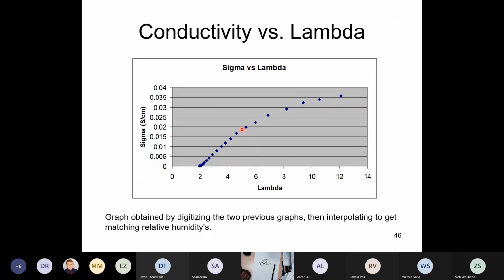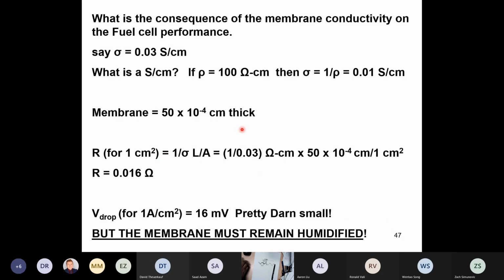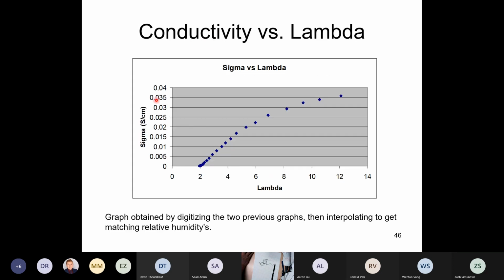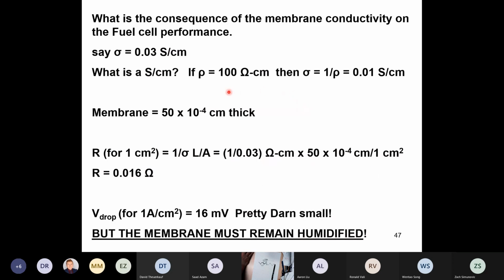Yeah, we'll just do one more slide because it's a good place to end after the next slide. So what's the consequence of this membrane conductivity on fuel cell performance? You can see about 0.03 Siemens per centimeter. This would be a decent value of the conductivity. So what is a Siemens per centimeter? Well, if rho is 100 ohm centimeters, then sigma is 1 over rho. It's 0.01 Siemens per centimeter. So if you don't know what a Siemens per centimeter is, that's what it is.